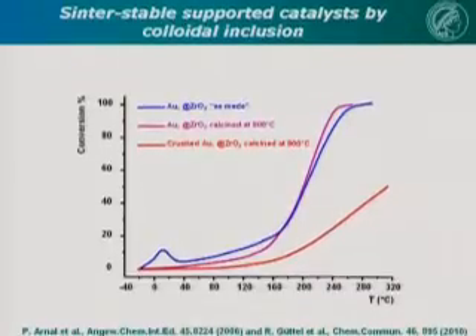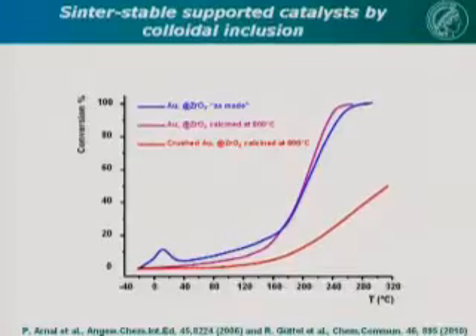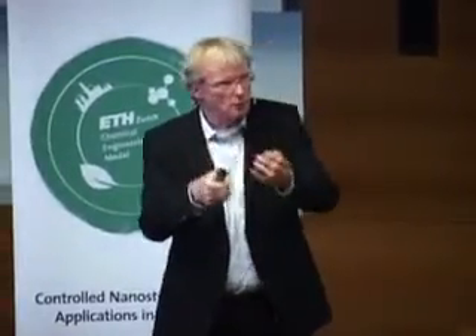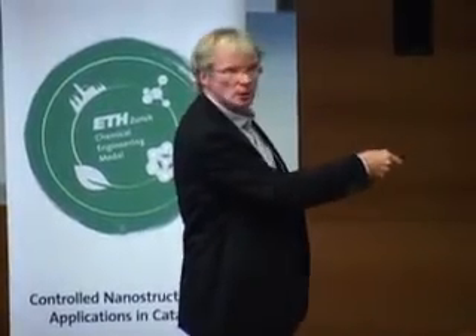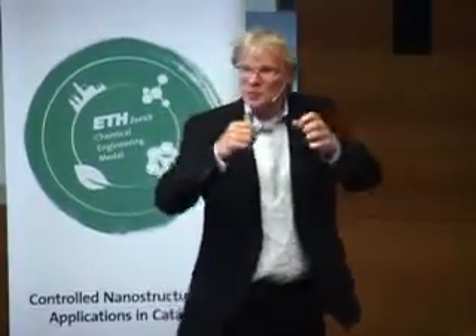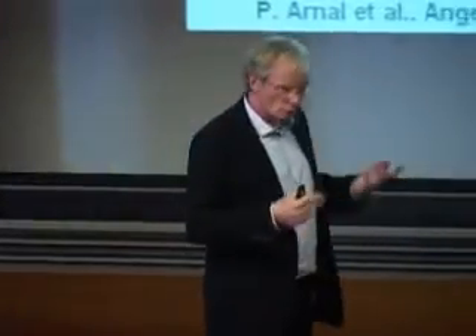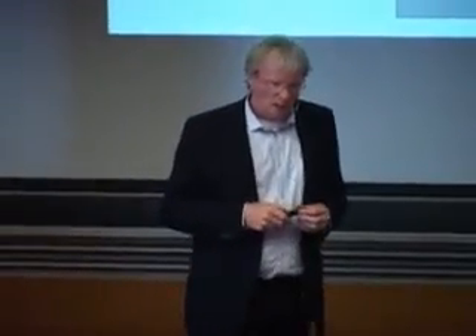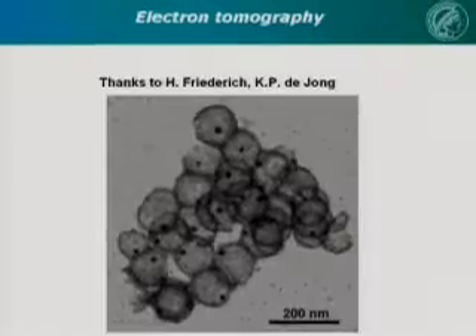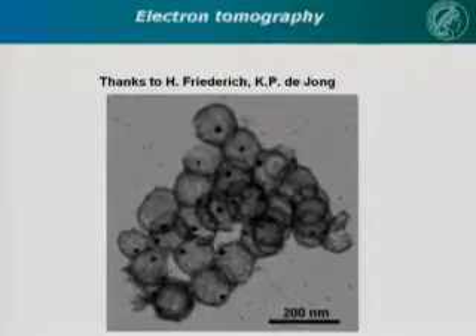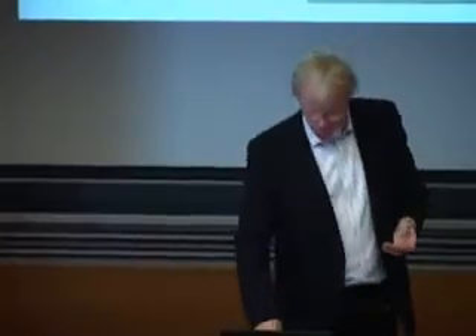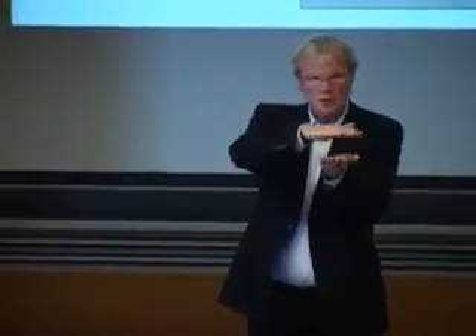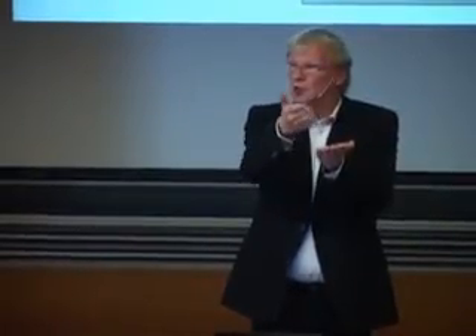You need much smaller particles to get higher activity, but that's not bad for the 50 nanometer size. If we calcine this sample at 800 degrees centigrade, it's essentially the same conversion curve. So no loss in activity. If we crush the spheres so that the shell is broken, and we do the same experiment, calcine at 800 degrees centigrade, activity is lost, and the reason is that the gold particles now sinter and form big gold particles. We don't have the protection anymore. This is the image, and I would like to thank Heiner Friedrich and Krijn de Jong for doing this tomography analysis, where we can really see that the gold particles are individually encapsulated in the zirconia shells. What they do is basically they record 170 electron micrographs and tilt the sample stage by 1 degree after each micrograph.